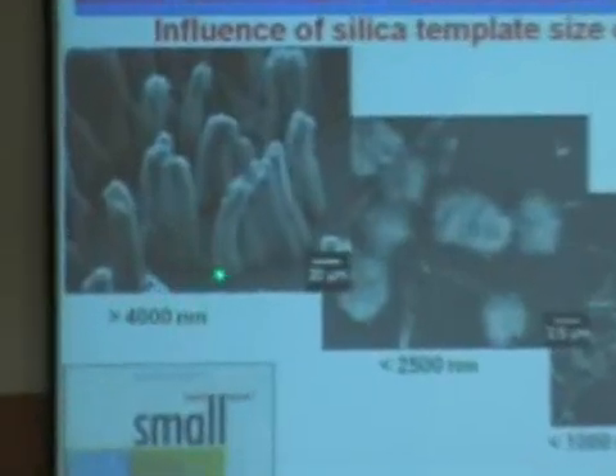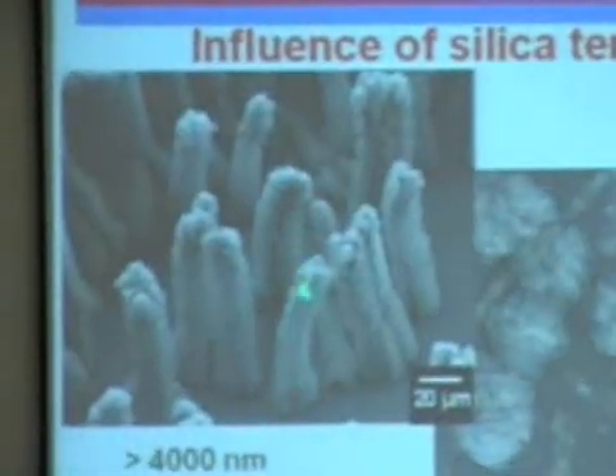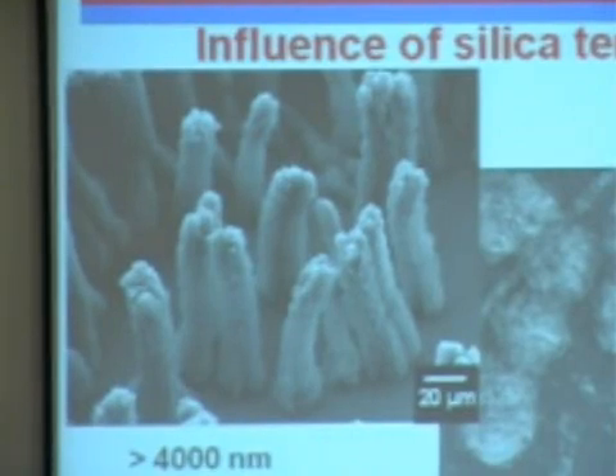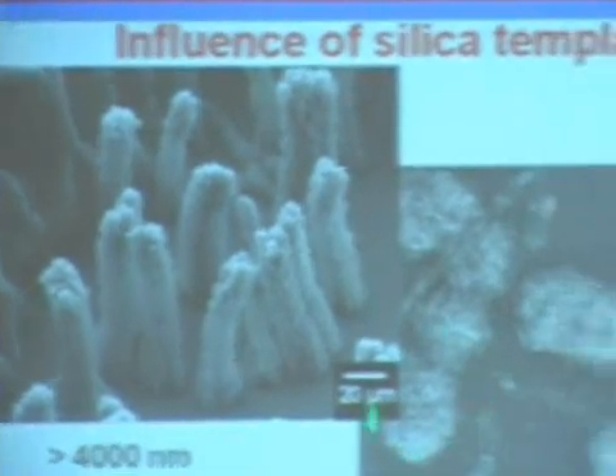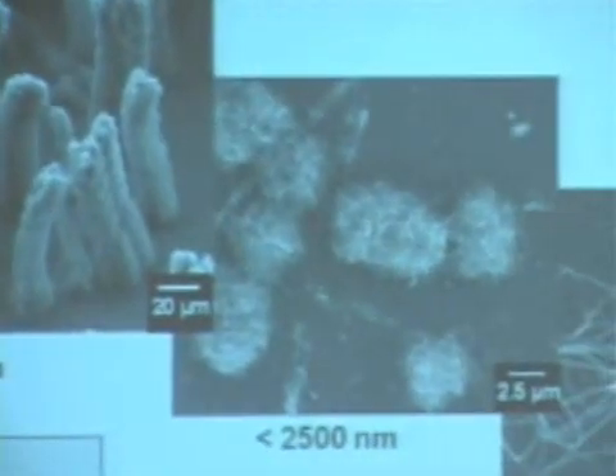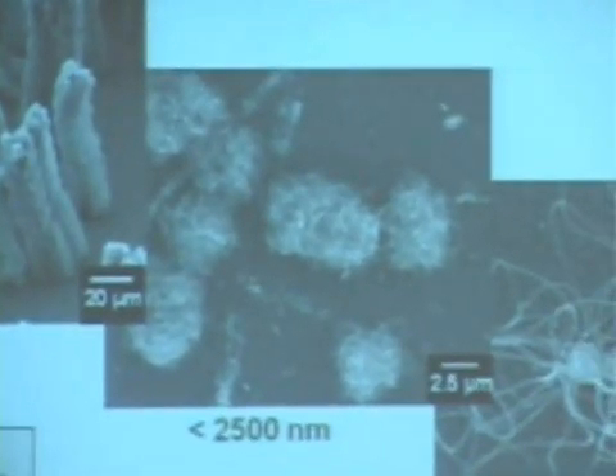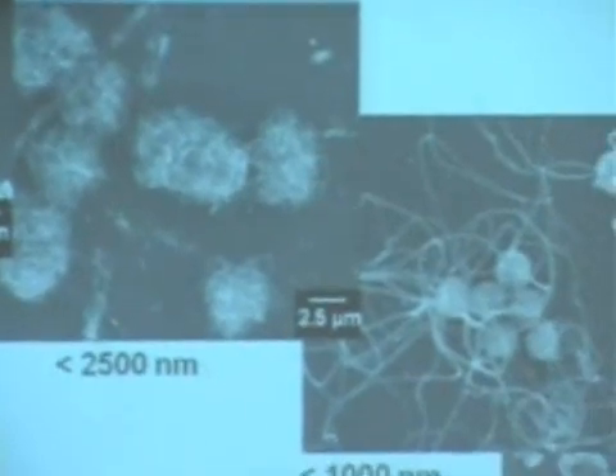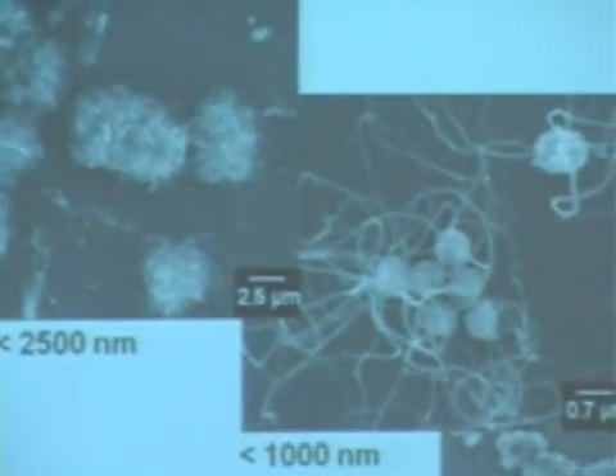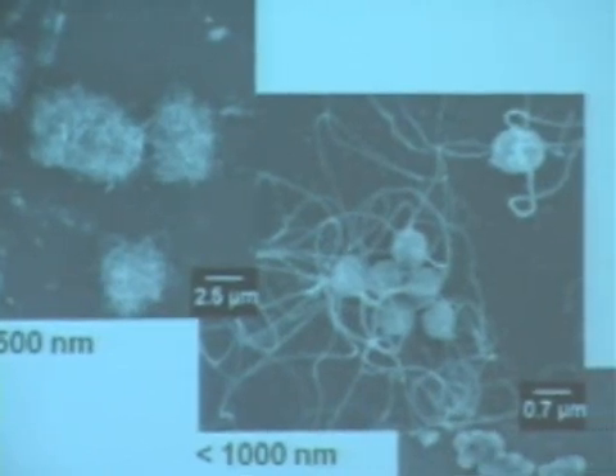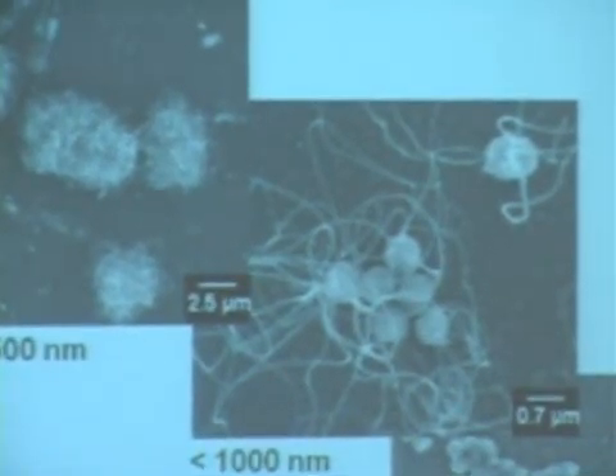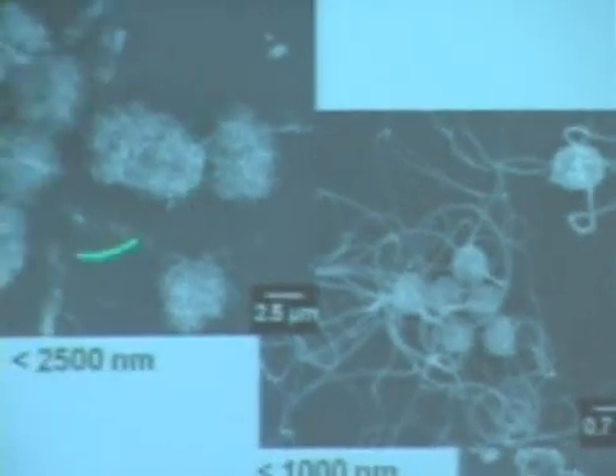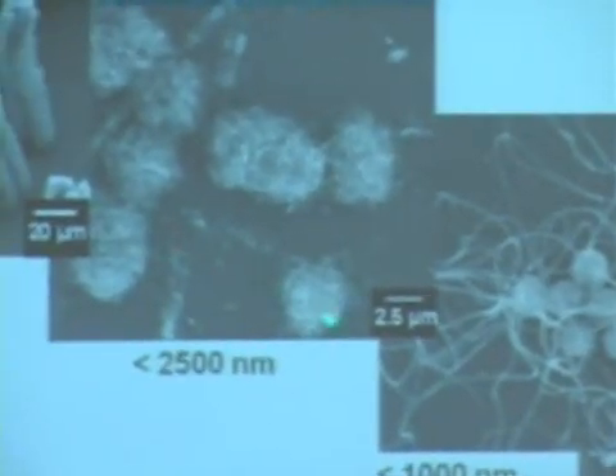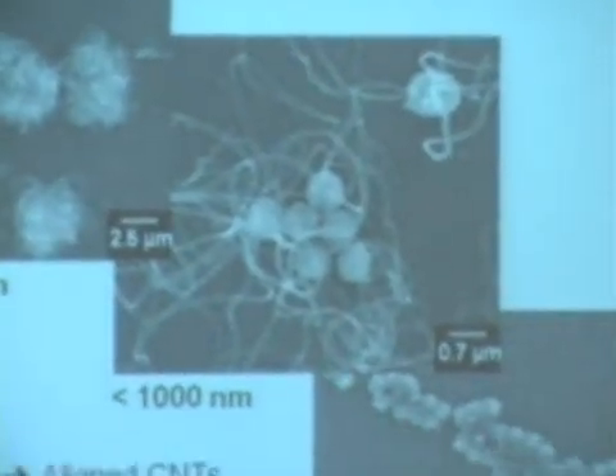Okay, but what happens when you decrease the size of the silica particles is these carbon nanotubes are not reinforced by each other anymore, and they behave like polymeric structures. That's because, as you decrease the particle size, the nanotubes tend to grow with a greater angular separation, and hence they do not have the scope to reinforce each other and get directionality. So entropy takes over, as opposed to enthalpy, thermodynamically speaking, and hence these curl up, and the nucleation also decreases as you decrease the size of the particles further, and all that you get is amorphous carbon.